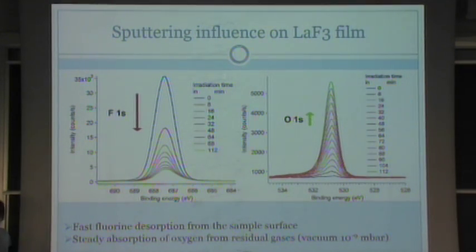Understanding of where the oxygen comes from can be shown from these 2 pictures. Here you can see a huge drop of fluorine. In the first 30 minutes, you've got a drop of the intensity. You lost 2/3 of your fluorine on the surface. And on the right, you can see a small step-by-step increase of oxygen, which points to oxidation from residual gases. So you have a vacuum in the chamber at 10^-9 millibar, and still you've got oxidation from residual gases, which was quite surprising. We didn't expect it, but the result is the result, and it's like this.